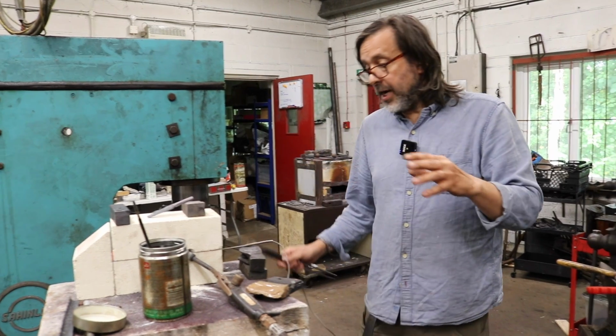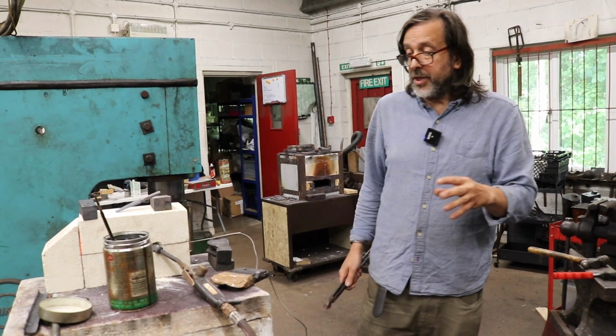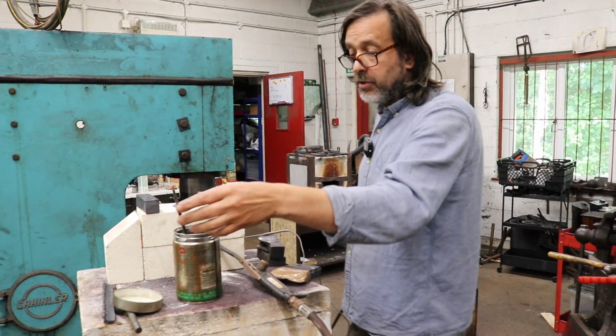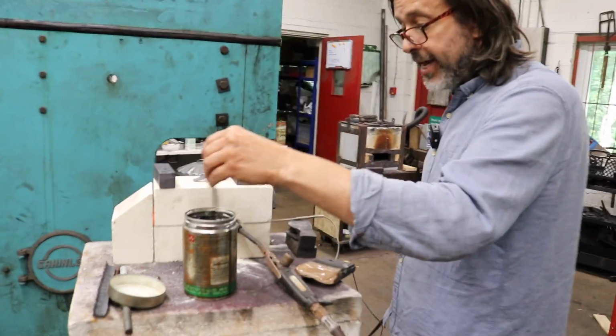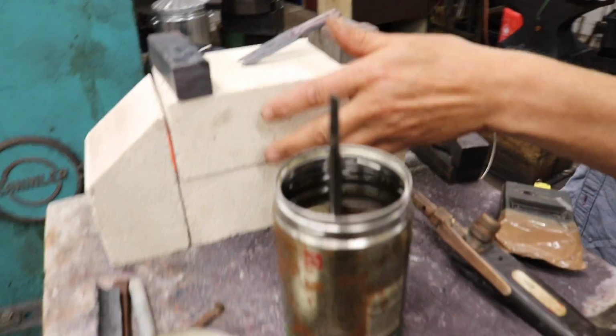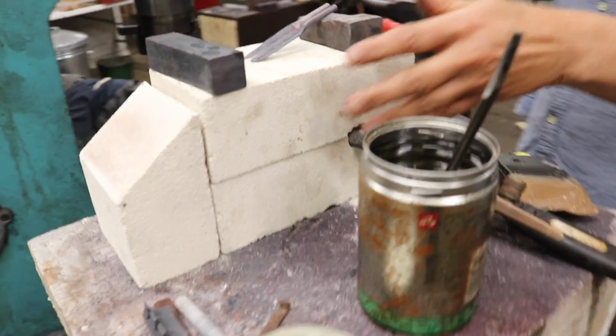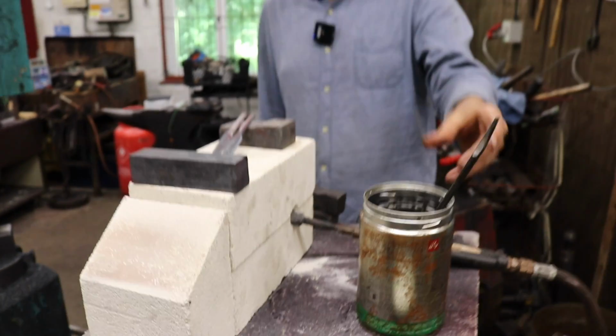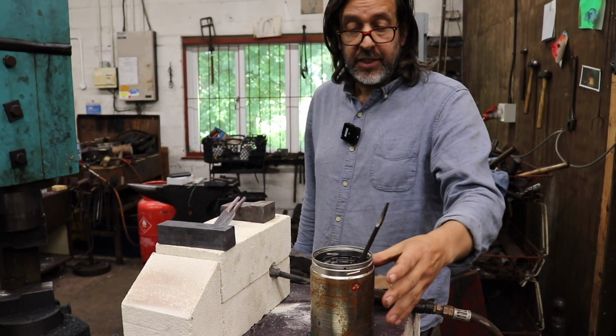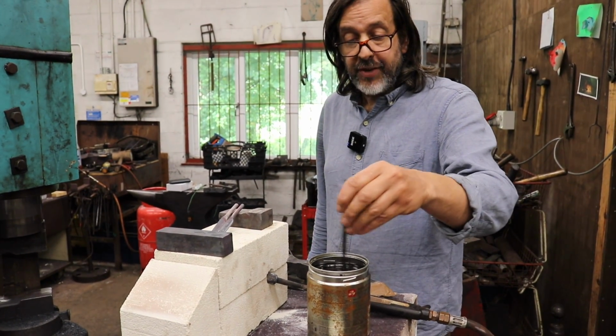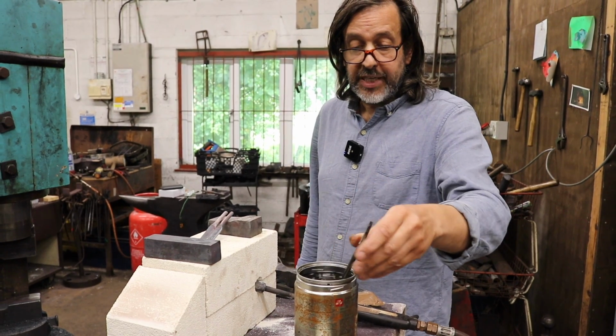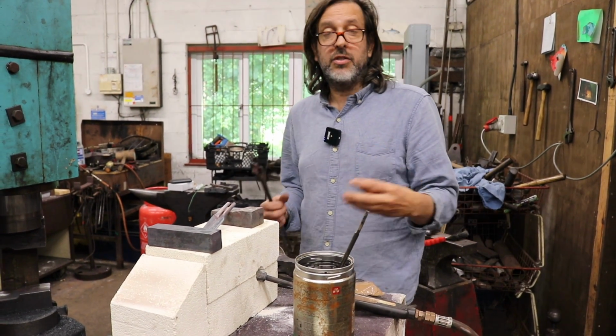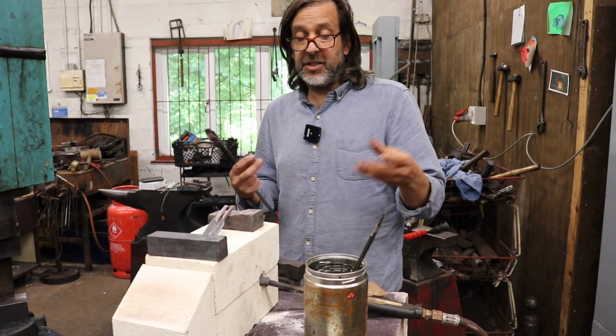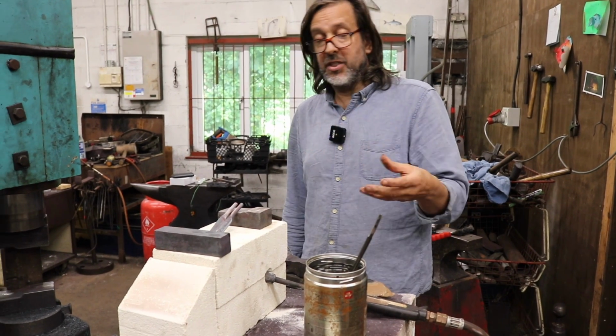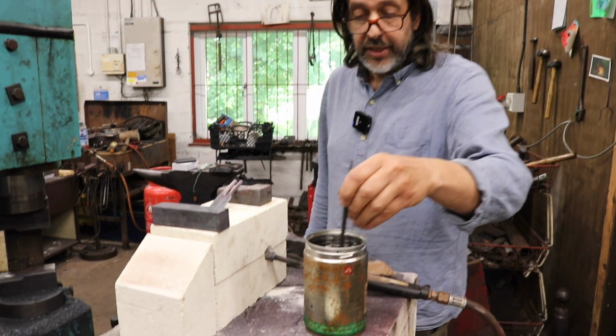I have got proper quenching oils which I normally use, but I'm going to quench in vegetable oil, which is just in this tin here, and I've heated it up. It was up against the forge here, and I know from experience, it sounds very hot, but 60 to 70 degrees seems to work best for vegetable oil. It needs to be quite hot to get it thin. If you get it too hot, it boils and catches fire before it does any cooling, but 60 to 70 seems to be a sweet spot.